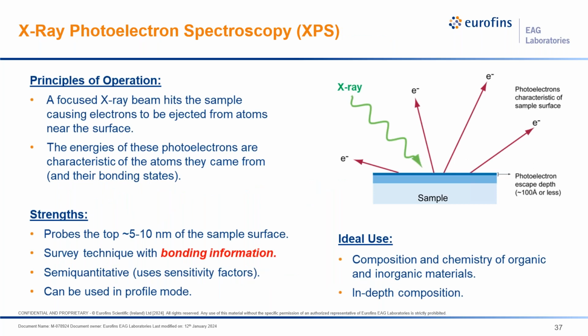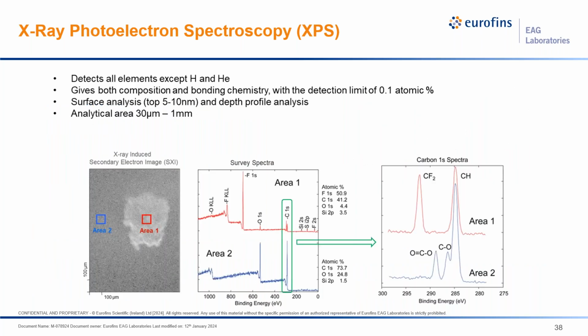XPS, we actually start with an X-ray, photoelectron, and we look at the secondary kinetic energies of the photoelectrons escaping the solid. And in this case, we actually have a sampling depth of about 10 nanometers. So similar to Auger, we are looking only at the outer surface. The additional information that we get from XPS over Auger is that we can actually start to see some chemical bonding information, next nearest neighbor chemistry. Auger, pretty much limited to just the elemental composition of the surface. So the example of that is shown here where there's just a thin contamination layer.